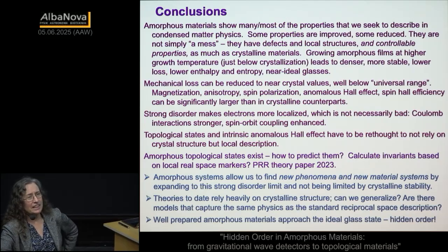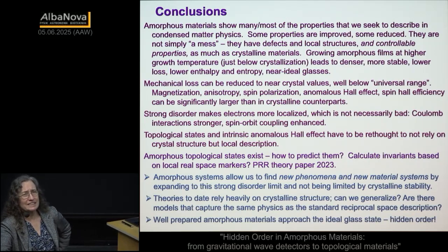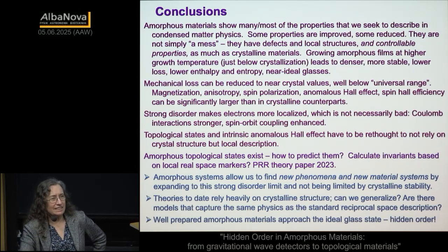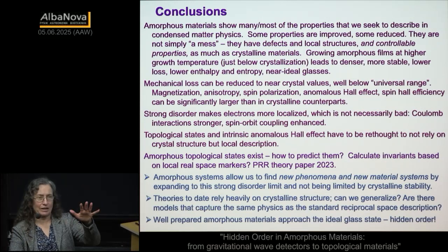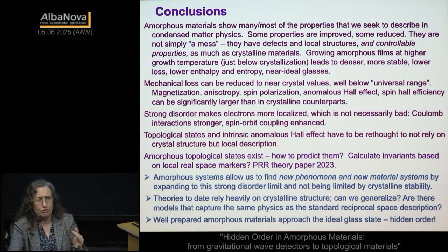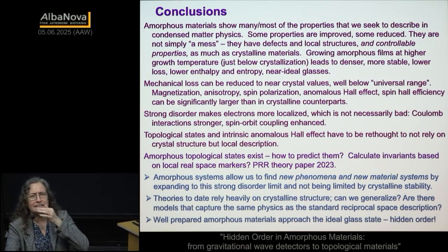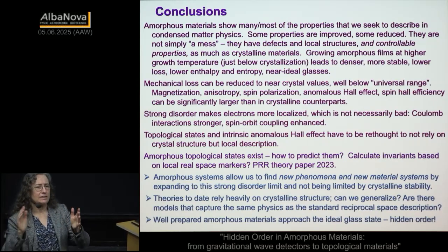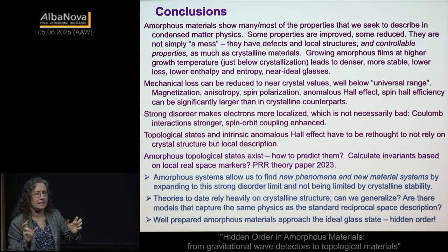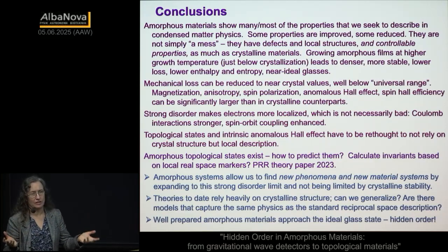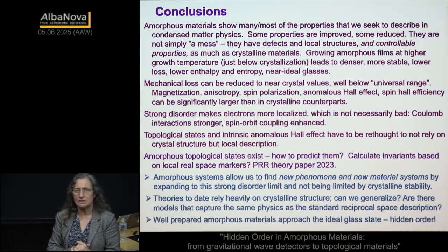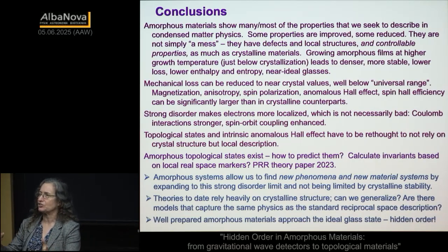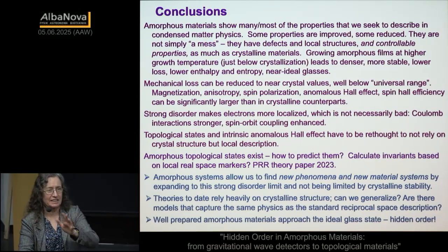And the end result was our amorphous silicon, it doesn't correlate. The mechanical loss went down by orders of magnitude. The dielectric loss only went down by a factor of 3. And it doesn't correlate. So the standard tunneling model is clearly incomplete, which everybody knows. It's quite obviously incomplete. Now I'm getting very specialized, so nobody else should worry if you don't understand a word I'm saying here.